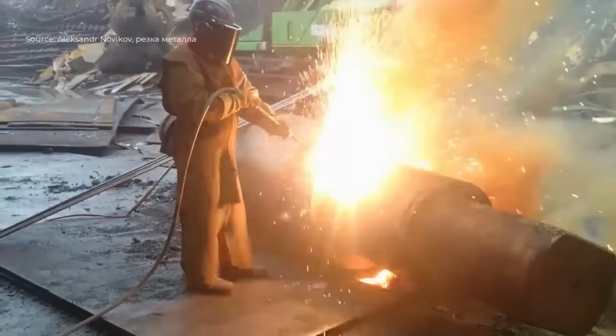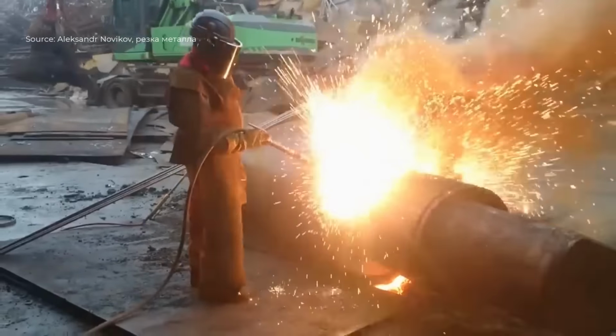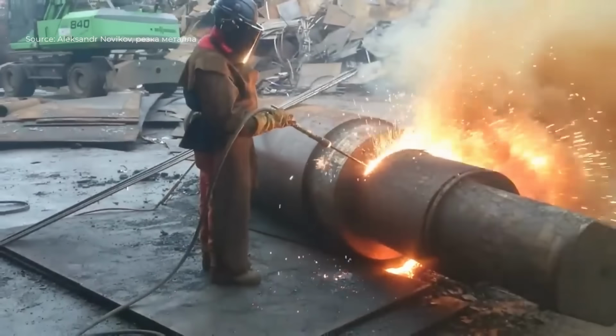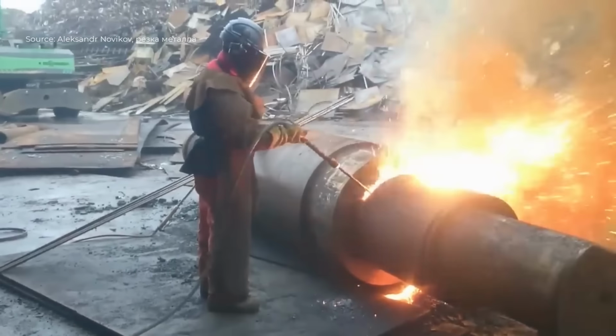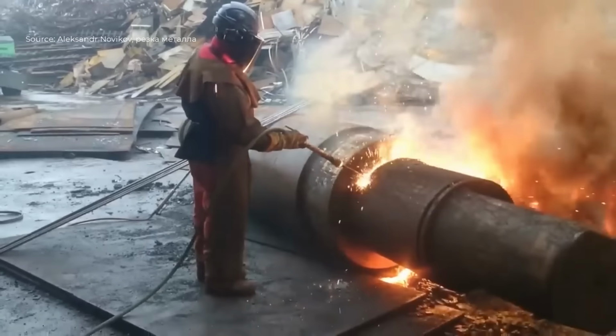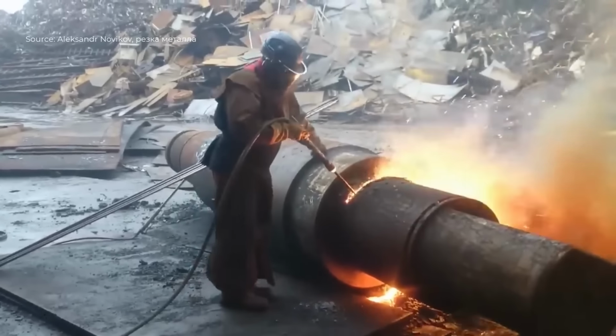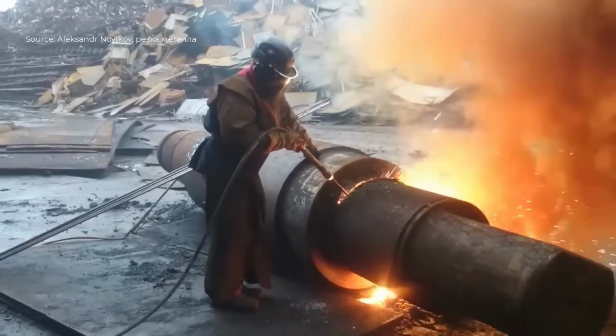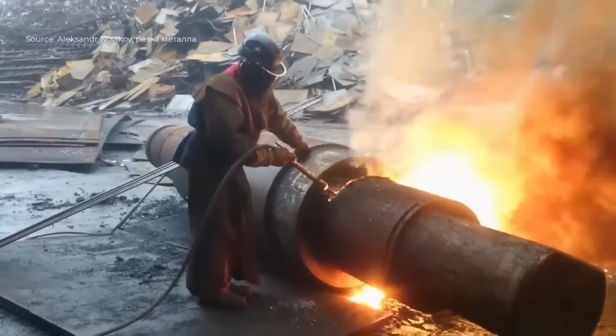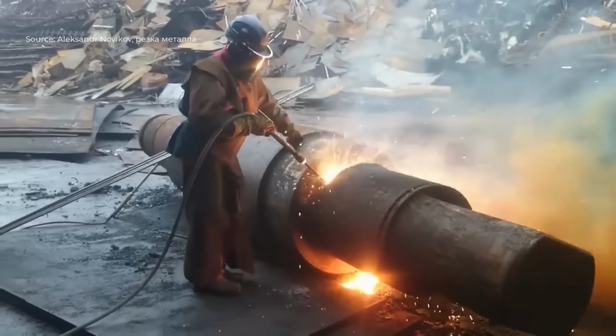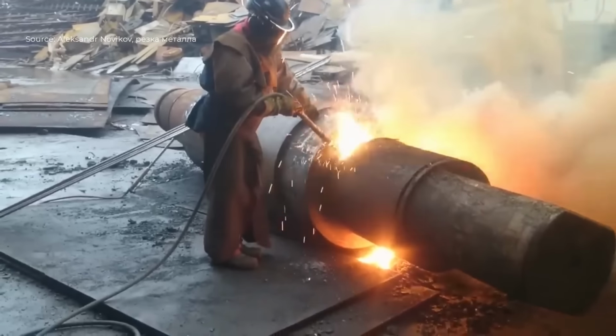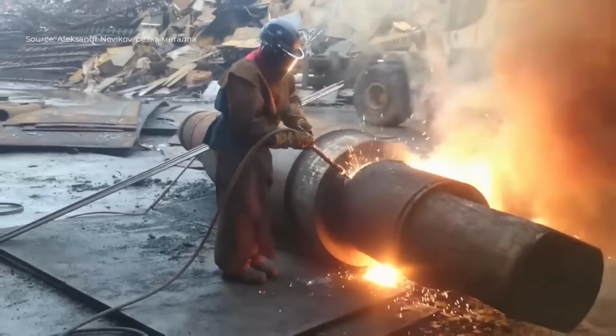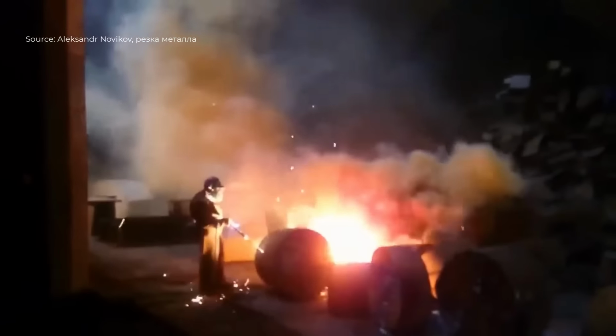During cutting, the operator directs the lance along the predetermined line on the shaft. The reaction between the steel tube and the pure oxygen creates a continuous burning effect, producing a stream of molten metal that falls away from the cut. Despite the enormous mass of the shaft, the process is remarkably fast. The lance burns, on average, for 3.5 minutes, meaning operators must work with precision and speed while maintaining steady control.